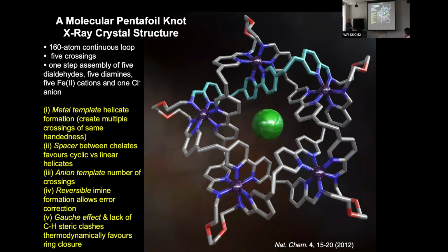And finally, by looking at the X-ray structure, we can see why these 2 oxygen atoms in the spacer are so critical to the synthesis. It's because if these oxygen atoms were CH2 groups, you'd have 1,3 steric interactions between the CH2 groups here and other hydrogen CH2 groups around the structure. So having these oxygen atoms removes that, and also having an